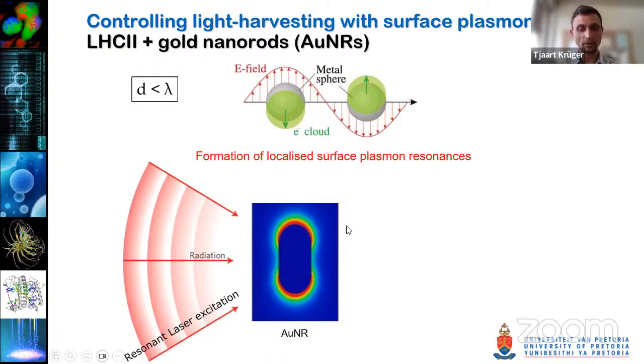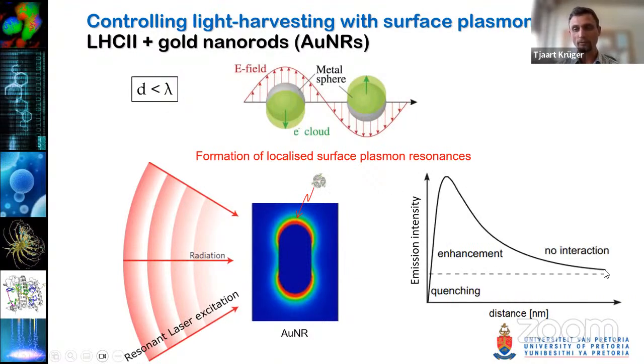Say one focuses light on a gold nanorod like this, and due to the curvature of the rod, the so-called lightning rod effect is formed. You have a large charge concentration here at the tips of the nanorod, and that leads to a large concentration of the electromagnetic field at the tips, forming so-called hotspots near the surface. Now, if you bring a molecule, for example our LHC2, close to the hotspot, so far away, it's not going to interact with the plasmon field, but as you get it closer, the emission intensity is going to be enhanced significantly because of this exciton-plasmon coupling, reaching an optimal level. Then when you get very close, in the order of a few nanometers, strong quenching is going to happen because of electron transfer from your fluorescent molecule to the plasmonic system.